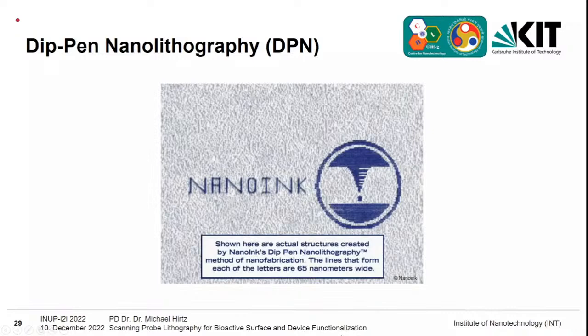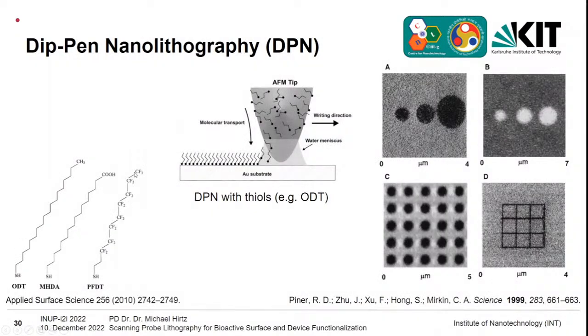So what you see now is not an animation anymore, but a pattern that was really created. And you can see, each of the letters, these lines, they are only 65 nanometers wide. So again, you go to a very, very high resolution. That's well in the nano realm. So if we go back here, this term dip pen nanolithography was coined by the Mirkin Group in 1999, a few years later. And they could really nicely show the different deposition of self-assembled monolayers in arrays or in lines by bringing the AFM tip over the gold substrate, and you can see that a water meniscus is building and then the molecules transfer over the surface.